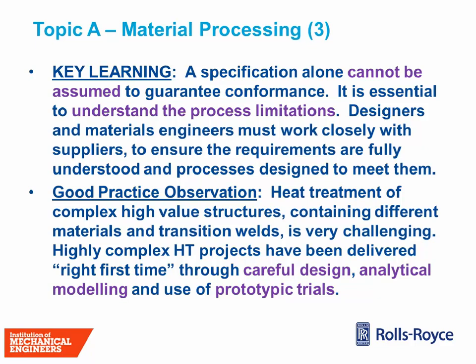So I've seen some very complex, very long lead, very high value structures made up of different materials with lots of transition welds, which require some sort of final heat treatment, usually because the complexity of manufacture leaves no option but to do a final heat treatment on one or another of different transition welds between dissimilar metals. And the risk there is that in trying to achieve the correct microstructure for one transition weld or one material, you can undermine the microstructure and the properties of an adjacent feature, an adjacent transition weld perhaps. So that sort of very complex, very challenging heat treatment tends to get a lot of focus.